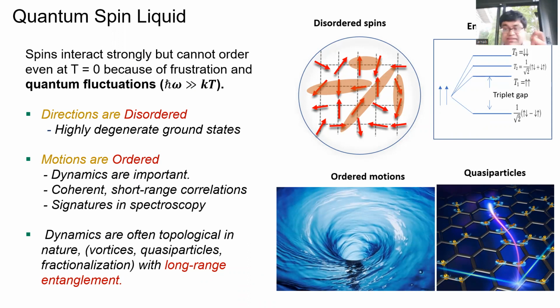And yet you won't get any signature in the statics, but you will get signatures in the dynamics. And you will have coherent short-range correlations, the signatures of which you should be able to get in spectroscopy. And as it turns out, in quantum spin liquids these dynamics are often topological in nature, so you can get vortices, quasiparticles, fractionalization, all coming because of long-range entanglement.